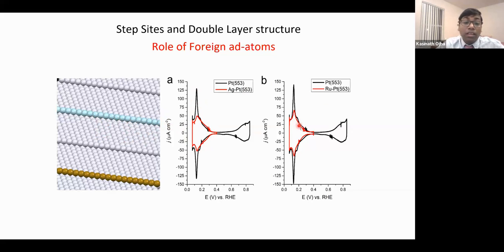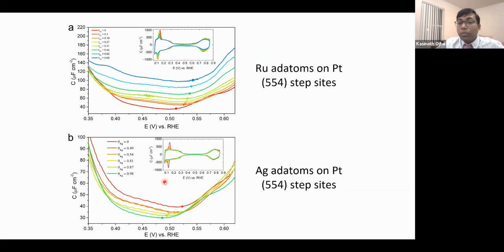Same for ruthenium as well. We also see similar things when we deposit ruthenium. But what happens if you deposit silver and ruthenium, and choosing those two elements also had a reason behind it, we'll explain later. And I did this with different step surfaces. What is interesting is that when you deposit ruthenium on the step sites, your double layer capacitance goes up, and the minimum in the capacitance curve also shifts to higher potential. But if you deposit silver on the step sites, your double layer capacitance goes lower and lower, and your minimum shifts to lower potential. That's very interesting, because in one case you are increasing the double layer capacitance, in the other case you are decreasing it.